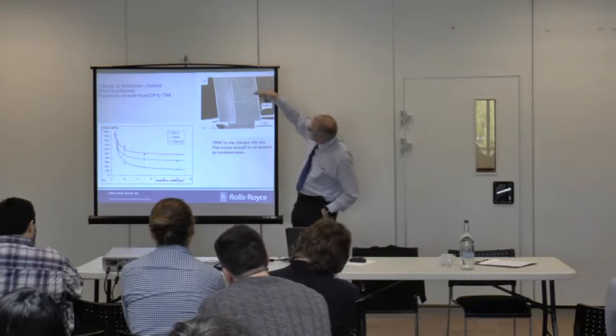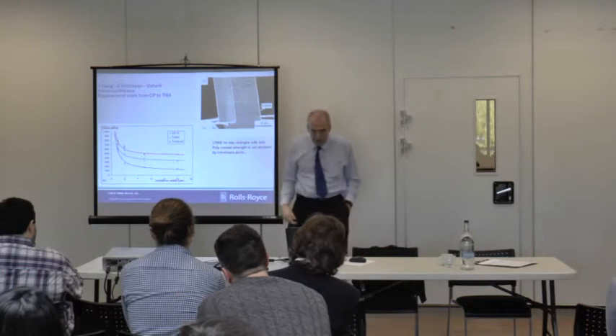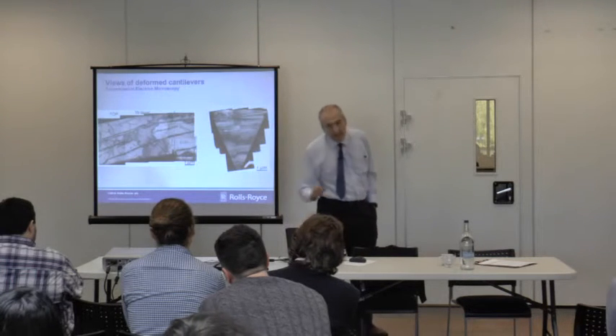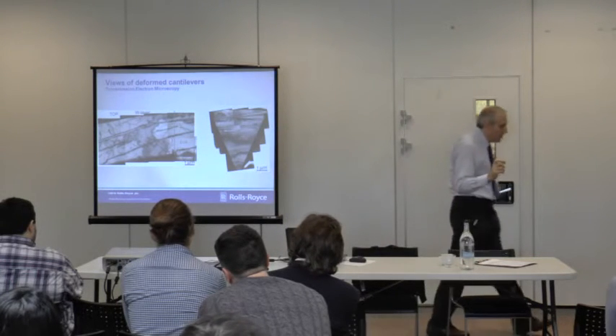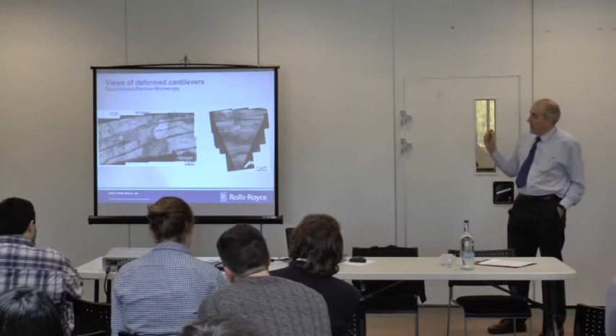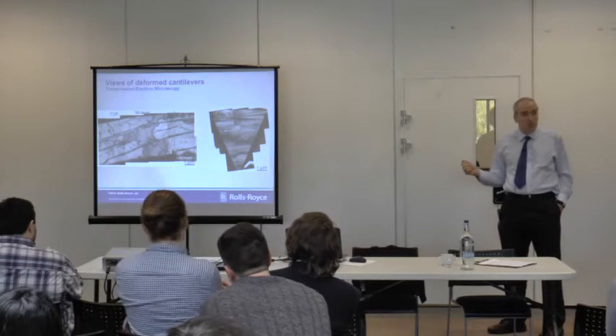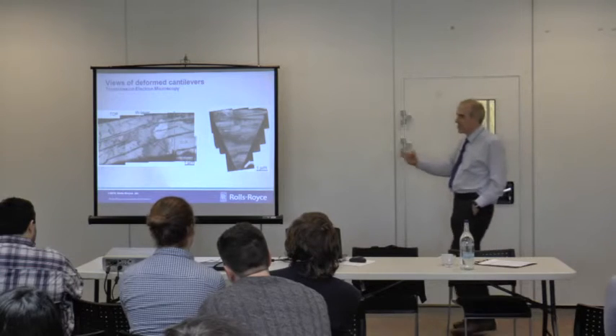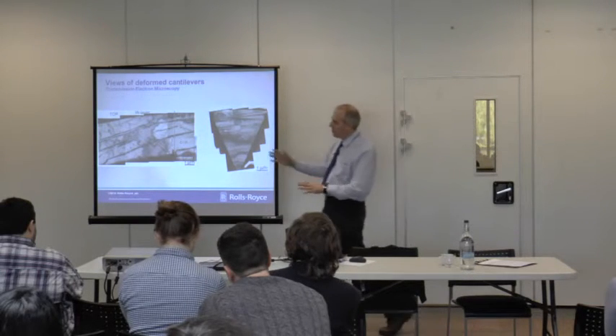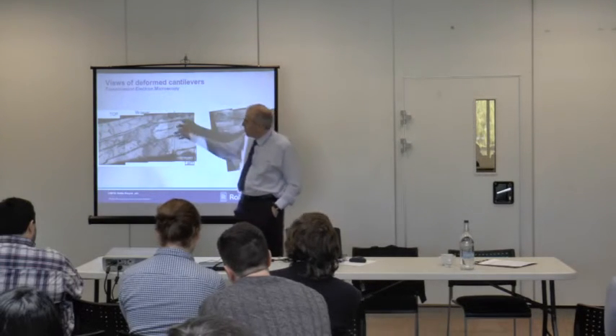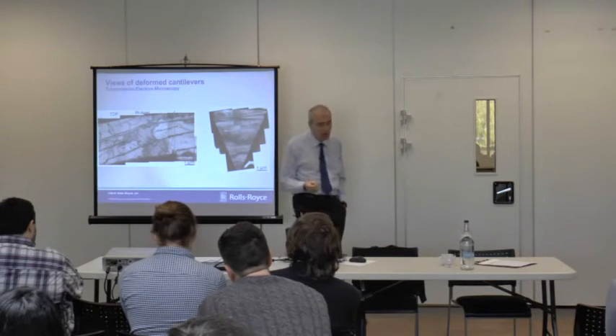In this case, we've got a dual phase material. So we've got HCP phase there and a BCC stripe in the middle. These things are slip bands, you can see. We can then take that, because the samples are sufficiently small, that we can look at it in a transmission electron microscope, and we can see all the dislocations that are left there. So a lot of the ones that have actually done the work and given the deformation have gone, but we can get some idea of what's going on. So that's kind of quite cool.